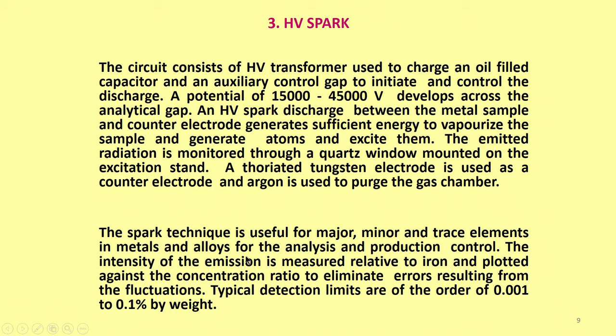So, the typical detection limits are of the order of 0.001% to 0.1% by weight. That means it is not a technique for trace elements, because normally whenever we want to analyze for trace elements, we want them in micrograms, nanograms and picograms. Picogram is 10 raised to minus 12 grams. Okay. So, it is not meant for ultra trace, but trace is fine, 0.001%, whenever you want to make an alloy.